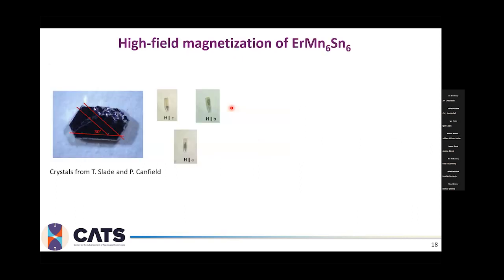So in that case, I got very huge crystals from Paul Canfield and Tyler Slade. Out of this one huge crystal, I was able to cut it in a way to measure it along all 3 different crystallographic axes. By cutting it here, we use the crystal to measure along the A direction. Then by cutting around 30 degrees from this dead piece, we use it to measure along the B direction. And then what was left, I cut out and pushed into this 1 millimeter diameter ampule.